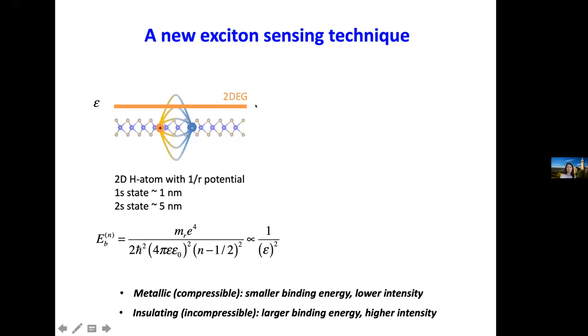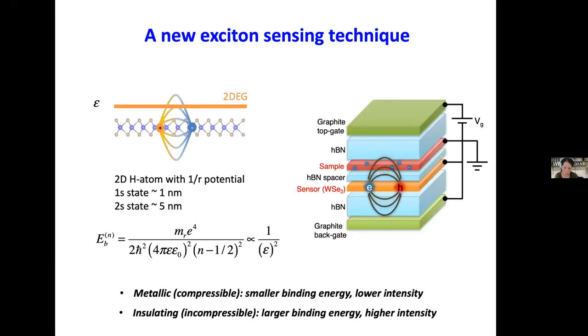And if the superlattice is insulating, we should see larger binding energy or higher intensity for the exciton. This is the realization of the scheme.